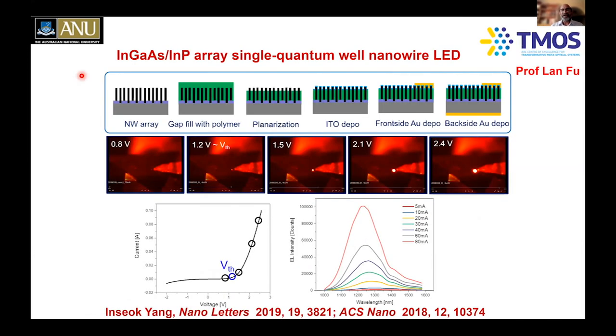Instead, before leaving, instead of making a single nanowire LED, she also made an array of nanowire LEDs. And the challenge is how to make contacts to the top one here. Essentially what we do is fill this gap between the nanowires with polymer. You selectively etch that using plasma etching and put some indium tin oxide and a metal on the side here and then the metal at the bottom so that you can inject current and look at the light emission. You can see the IV characteristic shows a diode-like behavior. Again, the higher the amount of current you're injecting, the higher the amount of light coming out.